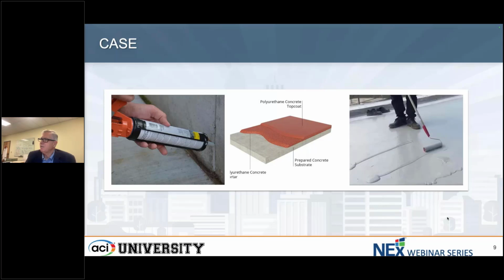It's also used a lot for deck coatings, especially in concrete parking garages and non-slip surfaces. Also to seal. So if you have a deck or a place where you don't want water to permeate through, it's going to be applied as it shows on the right with a roller, and you can put more than one different kind of coat on to get whatever texture you want. So these are the primary applications for polyurethane in the CASE type in construction.